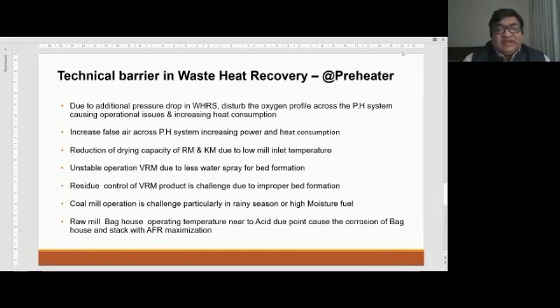Sometimes, especially during the rainy season, the drying capacity of the raw mill and coal mill reduces, which means the raw mill will not produce enough to keep your kiln at the optimum or maximum level, which reduces the consumption. It means your production can go lower than the optimum or desired point because the raw mill is not available.